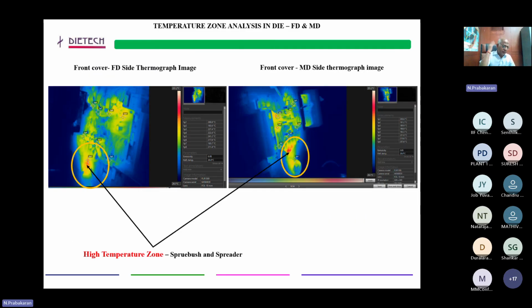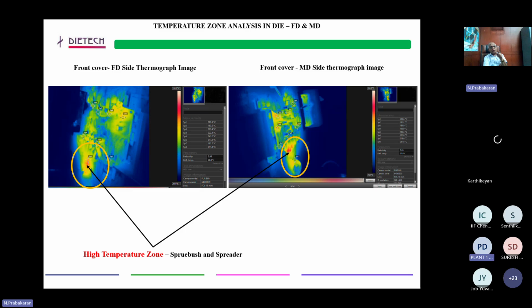These are all the inputs for further slides. If I'm doing a thermograph of the die temperature, normally the highest die temperature lies with the sprue bush and the spreader. One more clue I'll give: if you want to increase productivity, you want to reduce the cycle time. We can even measure the biscuit temperature. Normally we talk about casting temperature, but rather than that, we can take biscuit temperature reduction into account as one way to improve productivity and reduce the cycle time.